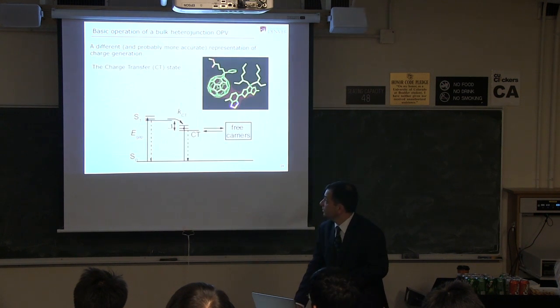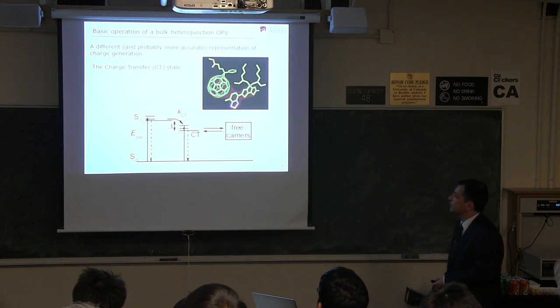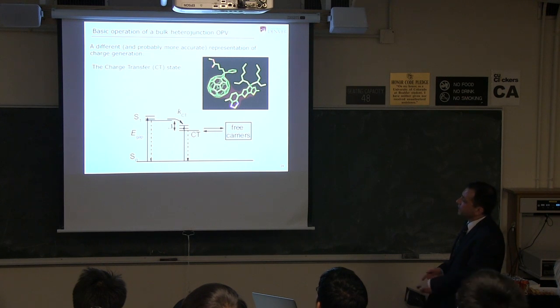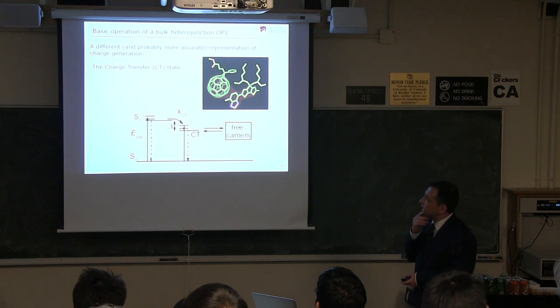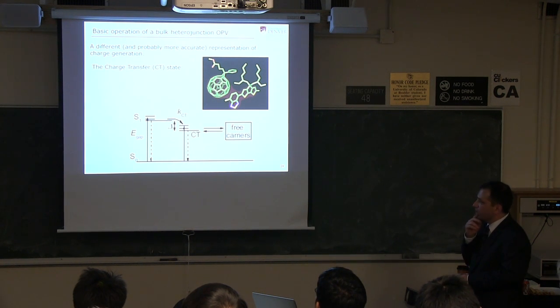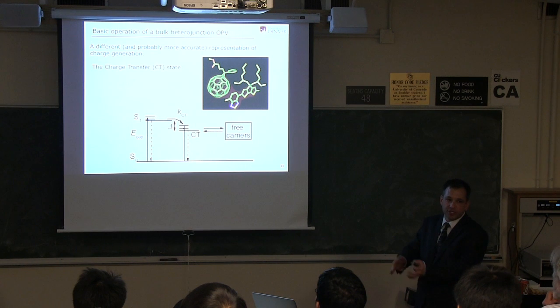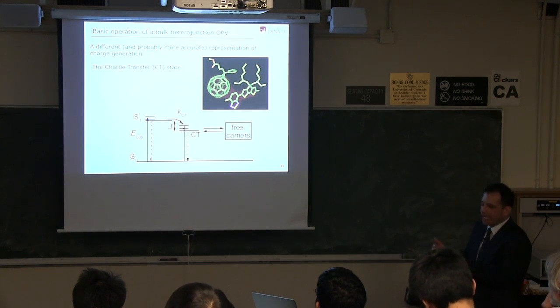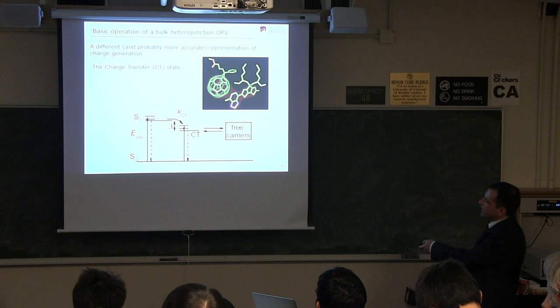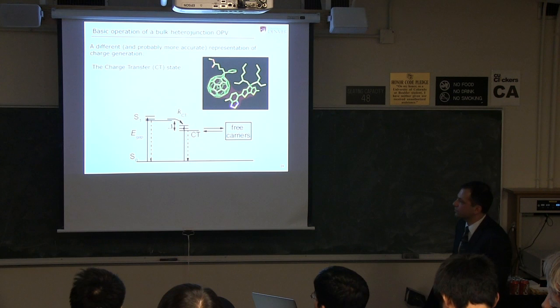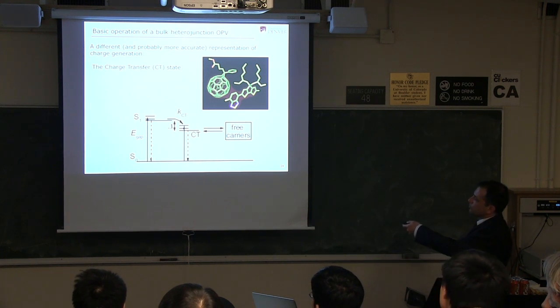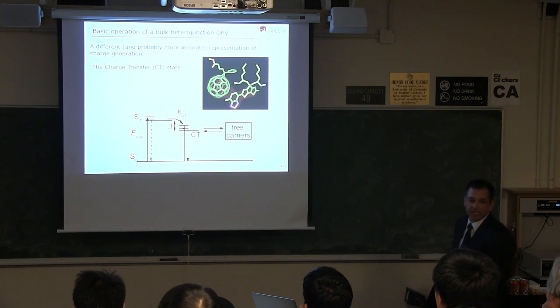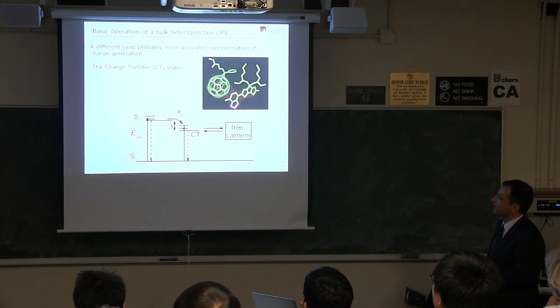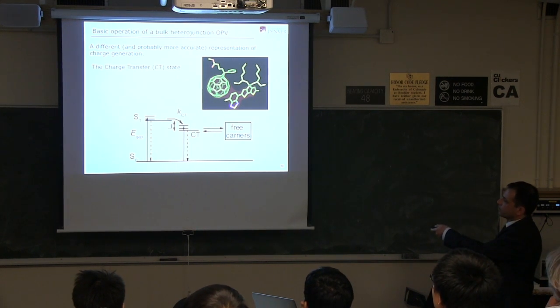Let me just mention the CT state in a little more detail. And the first thing is that it's a better idea to draw that whole process as a state diagram as opposed to a band diagram. That helps alleviate confusion between exciton energy and free charge energy, which you really can't put on the same plot. But if you do it as a state diagram, you say there's an electronic excitation up to the first excited singlet state, the S1 state. Then there is a charge transfer event to produce this intermediate, the sort of hiccup state, the charge transfer state. And then finally, hopefully, some free carrier generation.